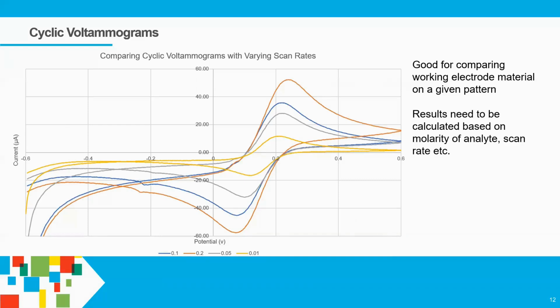So you may have a company that gives you cyclic voltammograms. Now, there's a time and a place for cyclic voltammograms. It's a very powerful tool. If anyone doesn't know, it's when you run a voltage over time and you measure the current produced. But you can have different scan rates, and with different scan rates, you have different intensities. Also, if you have luck, there's also a drift in your peak oxidation. So it doesn't really tell you that much.